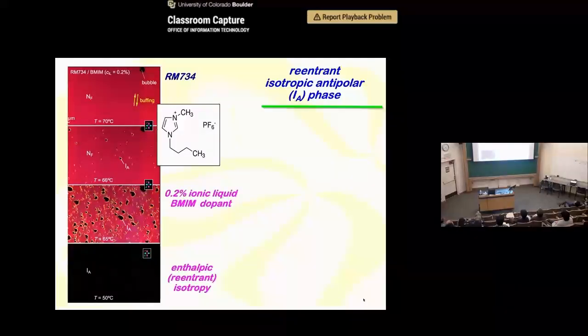Okay, so then I would say unexpected of these new phases, which we found, is this reentrant isotropic phase. So RM734, we add a small amount of this ionic liquid dopant. So these are organic ions that form a liquid phase at room temperature. So a tiny amount of this stuff creates a kinetic pathway to go to this phase.